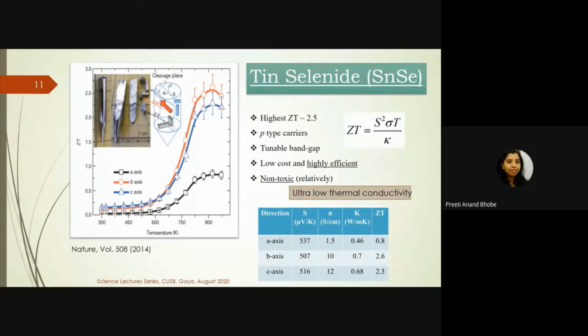The interesting thing was that it had broken all the barriers known to thermoelectric materials and was showing the highest thermoelectric figure of merit. When they studied the properties, they realized that it had a very low thermal conductivity. Actually, it was called ultra-low thermal conductivity. It was a very small value, 0.46, 0.7, 0.68 along the three axes. And because of this low thermal conductivity, if you remember the ZT equation, the denominator going very low meant ZT was going very high.